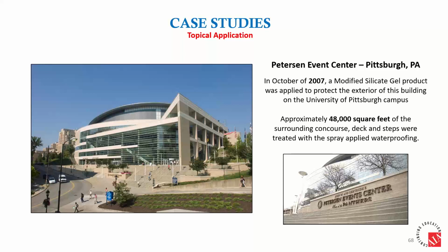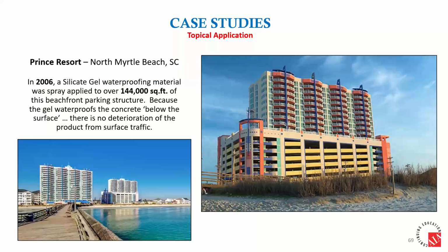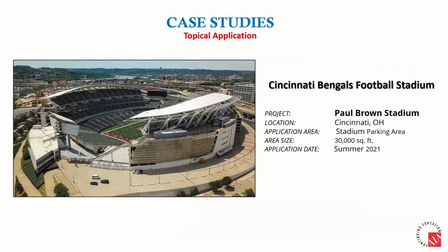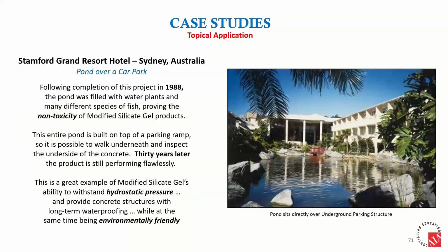This is at Pitt University. All of the areas you see around the Petersen Event Center, the stairs and all the concrete decks were all treated. Several resorts, parking structures at resorts in Miami Beach, or I'm sorry, in Myrtle Beach. This is Paul Brown Stadium where the Cincinnati Bengals play. That area directly in front of you is where trucks pull up to load and unload, and had significant cracking, and the silicate gel was applied there.